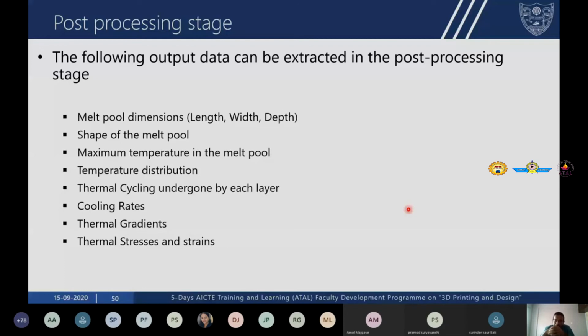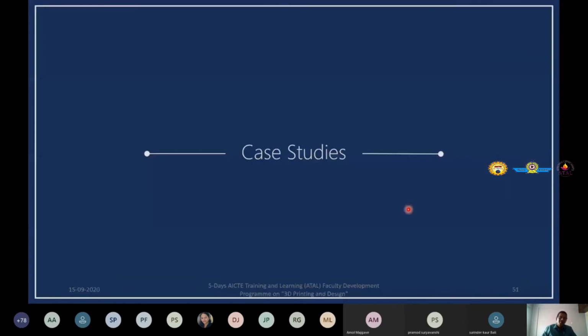We can find out the thermal cycling that's undergone by each layer. We can find out the cooling rates, which determine the grain size. We can find out thermal gradients, which determine the residual stress, and the cooling rates and thermal gradients together influence the grain morphology. We can determine the thermal stresses and strains. So now I'm going to present some case studies that we have carried out at NITK using computational modeling of laser additive manufacturing processes to understand and gain insight into these processes.